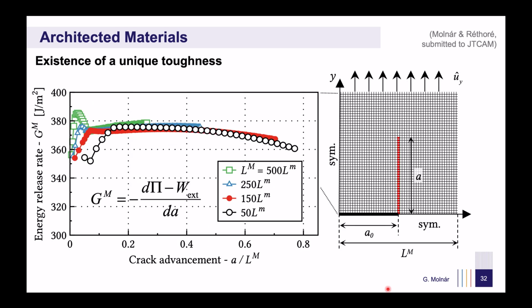Before constructing the model, we need to verify that a unique fracture toughness exists for a beam structure. To do this, we observed crack propagation in the beam model. By measuring the crack length and tracking the change in potential energy, we could define a critical energy release rate. We found that apart from initial fluctuation, this value remains constant, independent of the crack length or geometric features. This confirms that indeed the fracture toughness is well defined for lattice structures.